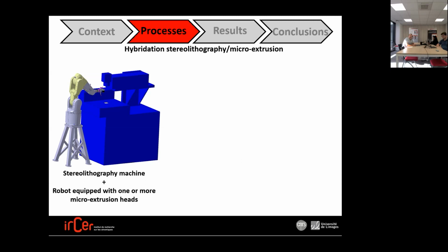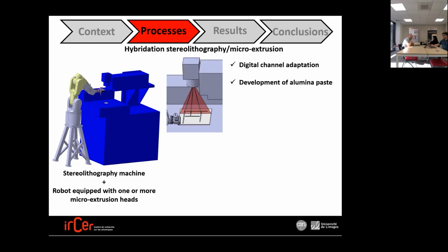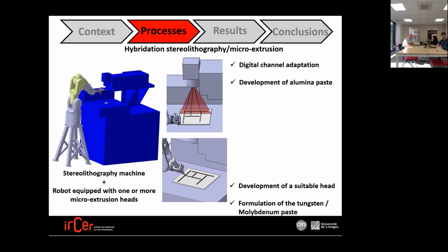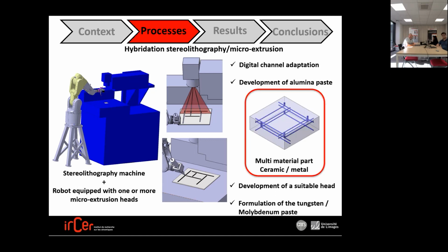So, the processes. The idea is to make a hybridization of the stereolithography process with a micro extrusion process. We have taken a 3D Ceram SLA device, and we have coupled it with a robot, which is equipped with one or more micro extrusion heads. The first step for printing a layer is to make the substrate shape with the stereolithography process. Then we use the robot and the micro extrusion head to deposit one or more metals inside the slice before doing the next slice. Repeating this slice after slice, we are able to produce a multi-material part that combines ceramic and metal.